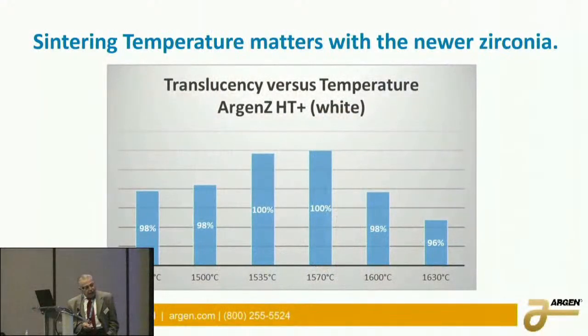And here I'll show you on our HT+, as the firing temperature goes up, we improve the translucency and then start to decrease it. So you have to be careful and follow the instructions a little closer with the newer brands of zirconia, because you may sacrifice some of the properties that the reason why you bought it is because it looked good, and if you overfire it, it may not look as good as you remembered it. Okay. Now this is for the white material.